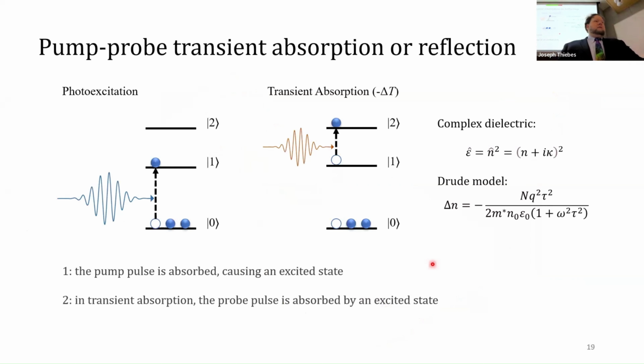Well, it turns out that when you have excited states in a material, it influences the complex dielectric or complex index of refraction, both of those things. And if you have an excited state, it can be further excited through absorption, and that's transient absorption, when the excited state itself absorbs more energy. Also, just having the excited states in the material can influence the real part of the index of refraction. You get a decrease in reflectivity. So the bottom line is either you're absorbing more light, or you're reflecting more light or less light, but somehow there's going to be a change in how much light you see at the detector.